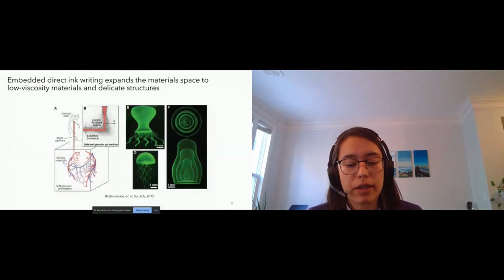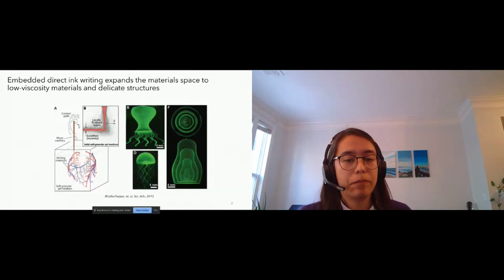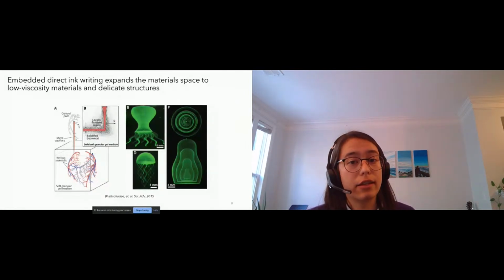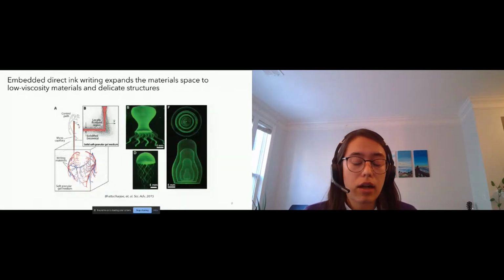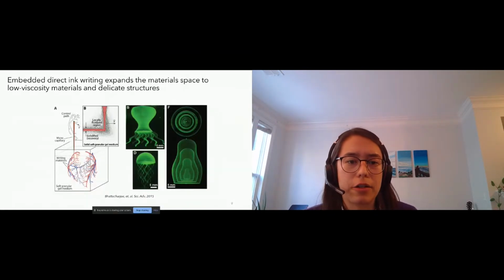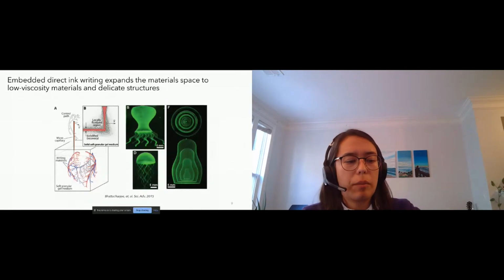The way that this works is you have a print bath that is full of a support fluid. Usually that fluid will have a yield stress and it'll be shear thinning, just like those materials that I talked about in the last slide. So things like carbopol hydrogels or laponite hydrogels will be good support baths. You embed your nozzle into that bath and then write out continuous filaments for embedded direct ink writing, or you could print out droplets for embedded droplet printing.